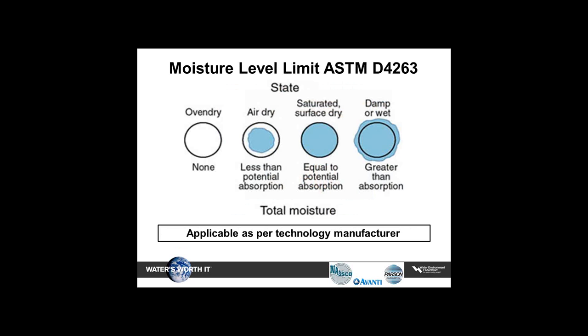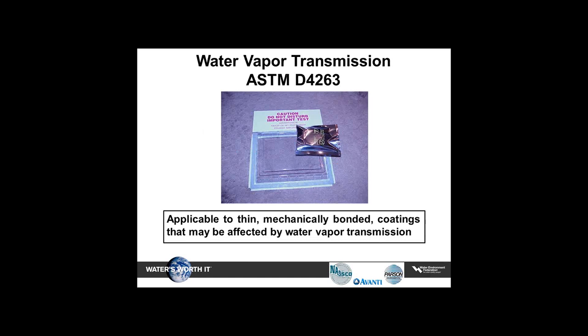We've talked a little bit about moisture levels. This is something that is usually defined by the technology manufacturer, not the applicator. The manufacturer will determine: can this particular product be applied on a damp or wet surface, or does it need to be saturated surface dry, which, as Jim said, feels cold but is not wet, or does it need to be perfectly dry, where there's no real cold or moisture at the surface? So different products have different requirements, and these are defined by the manufacturer.